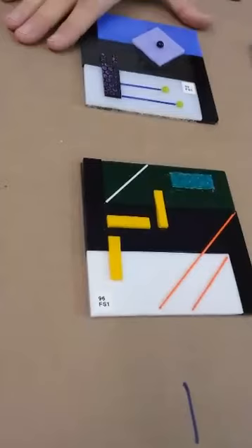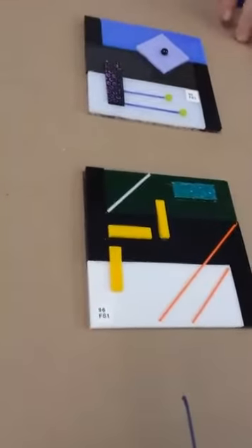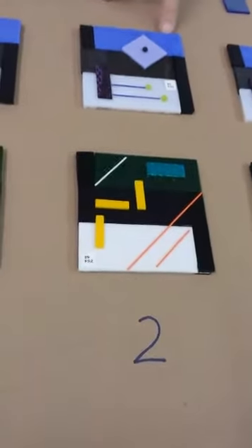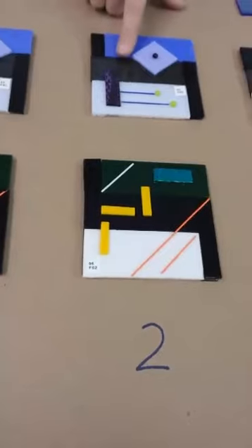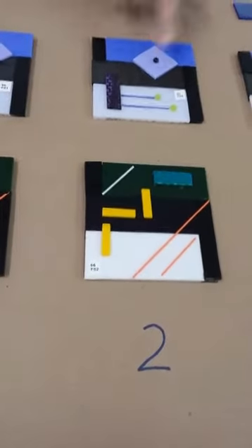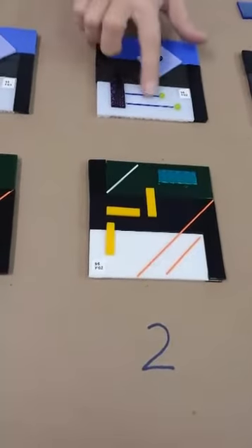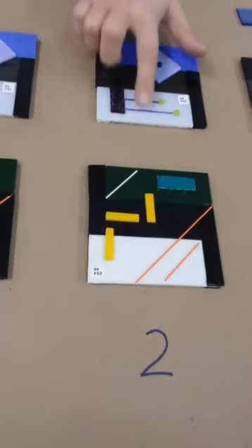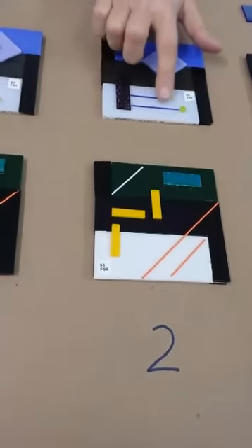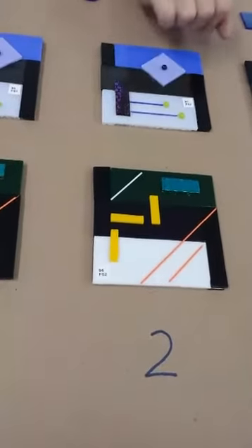So I fired it, I finished it, I ran my next schedule. I went roughly 40 degrees higher. That's the only thing that's changing between all my stages of my tack fuse and my final fuse: about 40 to 45 degrees. So the next phase was just a little hotter. I could see that my corners rounded over a little bit. My lines are a little smoother in here. My dot barely moved.